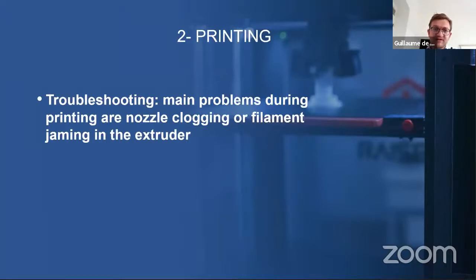Filament jamming is something that can happen for several reasons, but usually it's linked more to printing parameters not being the right ones. We're printing too fast, or we're not printing at the right temperature, or something of that kind. Again, the filaments are quite brittle, so everything that's out of line in terms of printing parameters may end up with that kind of problems.